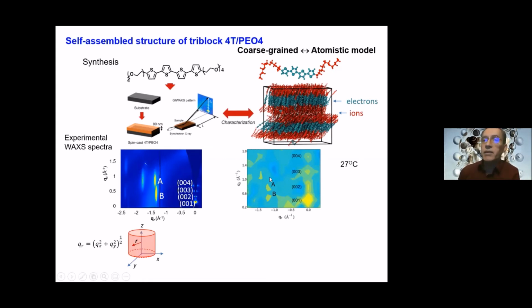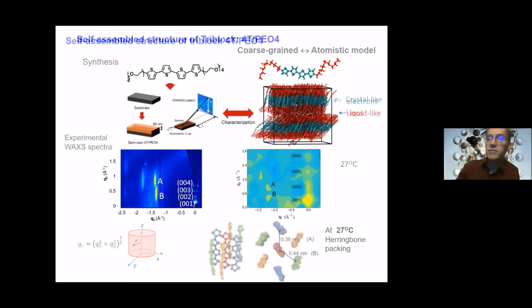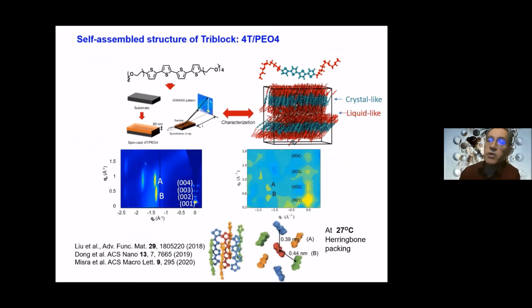And now in comparing our structure factor to theirs, there was a doubt that they didn't know exactly what these A and B diffraction peaks were. So they knew what these peaks over here were, which are the same here. Those correspond to a layered structure. So that much we know it's a sort of lamellar phase. Now this A and B could be easily seen in our simulations. And they corresponded to 2 key distances between these thiophene ring columns that form. And those distances are characteristic of the so-called herringbone packing.